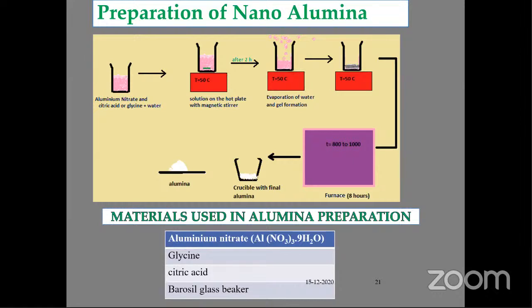But at a temperature of 900 degrees centigrade only, you will get the pure alpha alumina. At 800, it is partial. It's a combination of alpha and gamma.